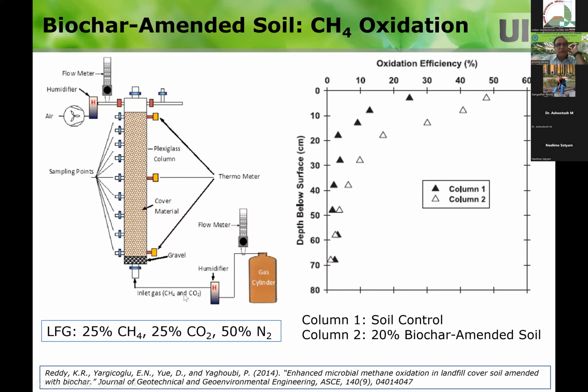And then we put that one and we injected this simulated methane, simulated landfill gas. Landfill gas is generally 50% methane, 50% CO2, but in this case we used 25% methane, 25% CO2. The rest is nitrogen. So basically, we wanted to see what happens to methane and CO2 as it comes through it. We have ports to collect the samples and analyze them, and then we collect the gases that are coming out, and see what the composition is and also what the flow rate is.